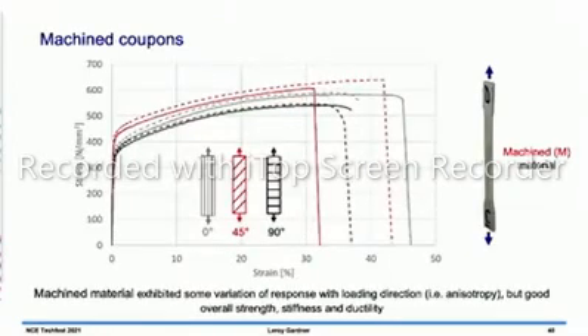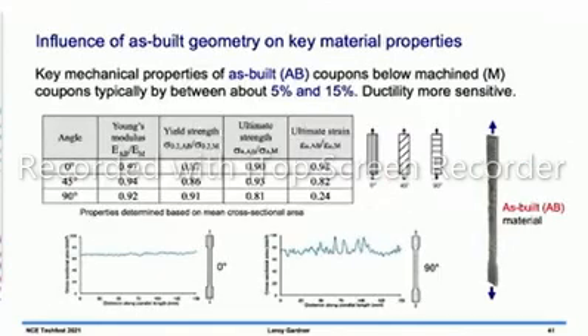And these are some typical measured stress-strain characteristics. And what you can see is that there's a bit of directionality to the material, so the properties are a bit different in different directions. That's called anisotropy. But overall, we've got good strength, stiffness, and ductility. So that was for the machined material.